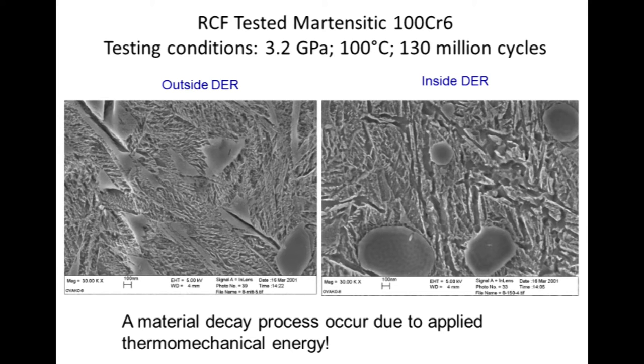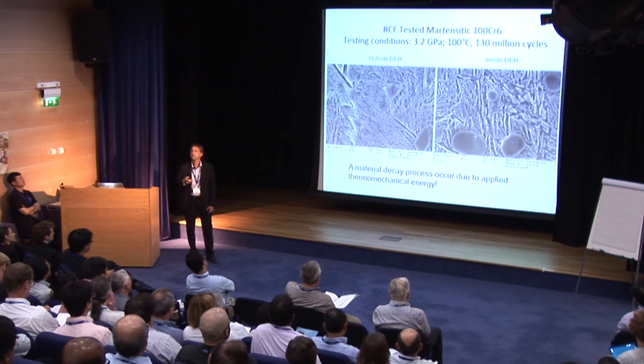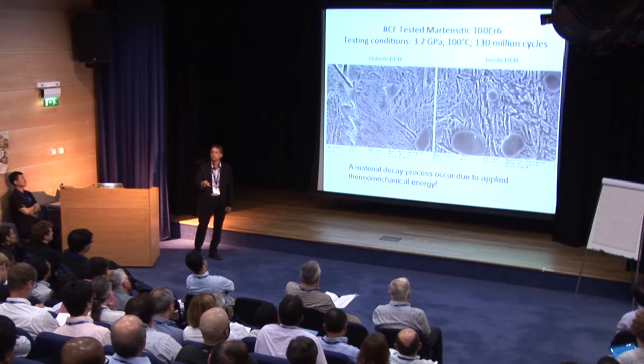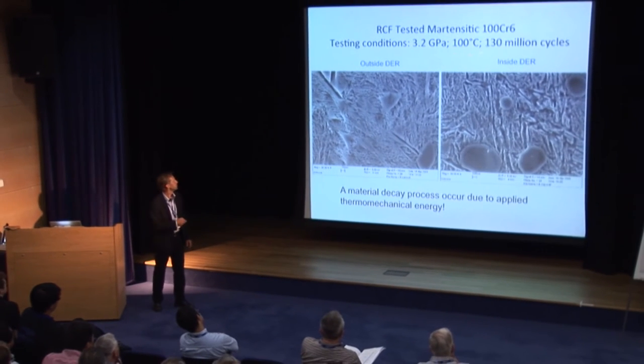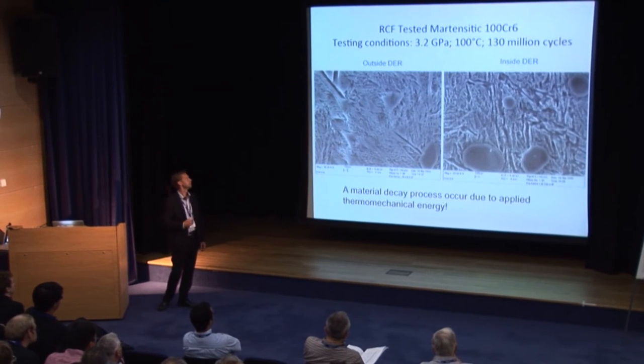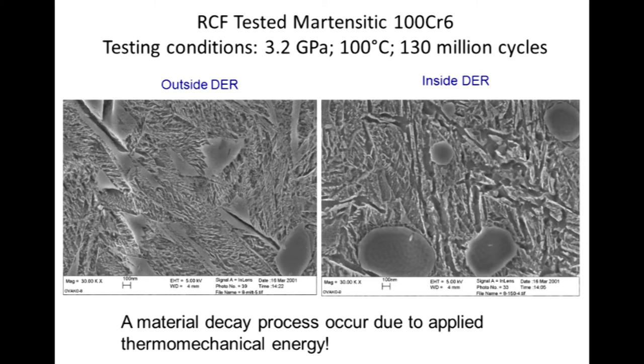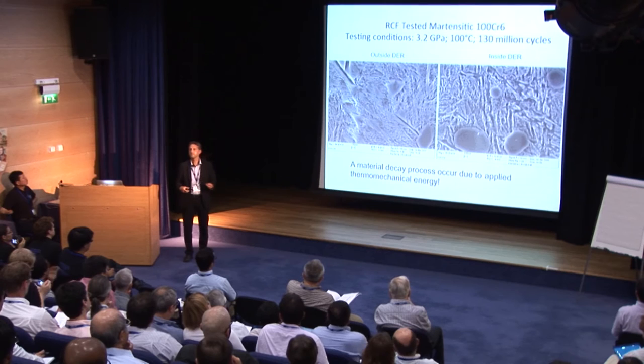So this process doesn't happen just for fun. It happens because you put in stress, you have a certain temperature, and it develops. So it is a process that happens in the material. We have done this test, looking at the very much loaded zone, and compared that to the same sample, but away from that. So if you test this rolling bearing material, a 100 chromium 6 material, at a high load, fairly high temperature, fairly long time, and then you take the scanning electron microscope and have a look where it's not loaded, it's the same sample.